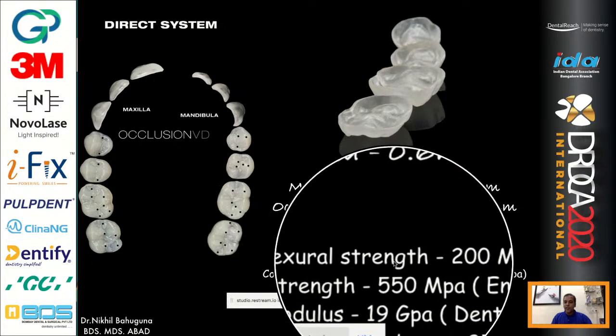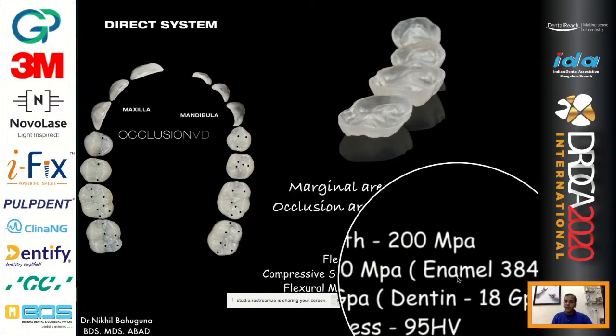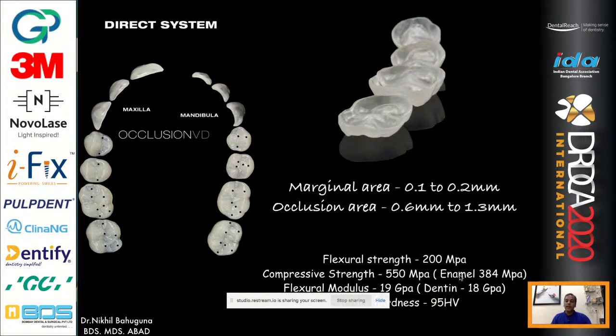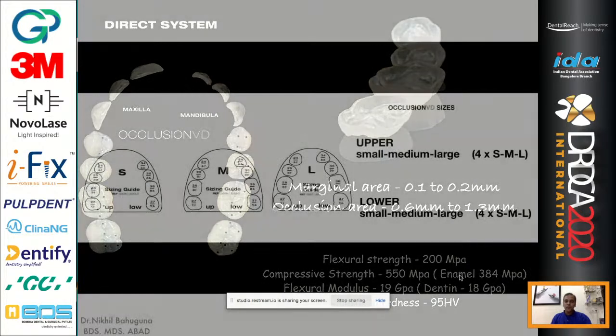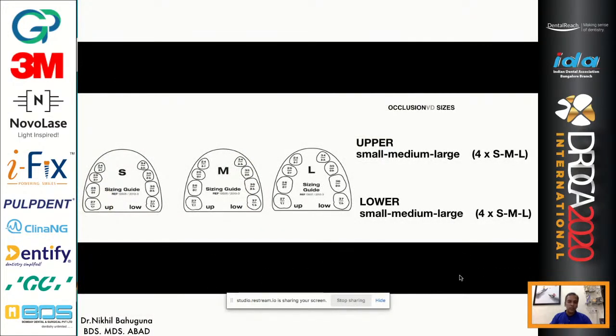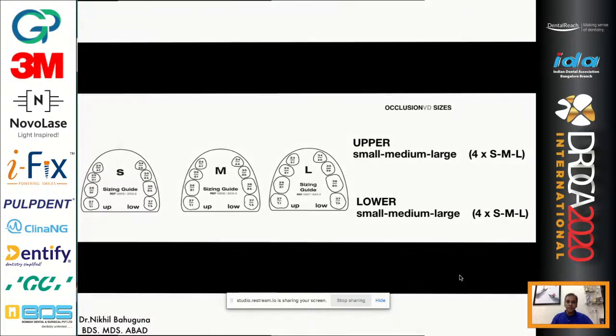And now comparing it to nature, the compressive strength of the VD is 550 megapascals and enamel is 384. The flexural modulus is 19 and the dentine is 18. And that's why the tagline is the difference of this material is in its similarity with nature. Comes in different sizes. You can choose the mesodistal width and the size accordingly.